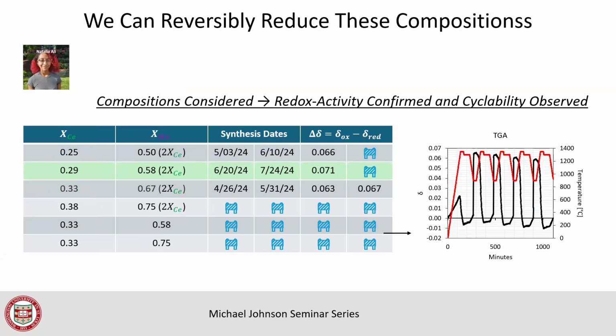She then went ahead and took those compositions and did a process called thermogravimetric analysis, TGA. TGA basically is an oven that can measure the amount of mass produced by a system. So if you were to put an ice cube in a TGA and heat it up, you would eventually see the mass of your sample decreasing and decreasing until mass is zero. So all the water is vaporized and it's no longer in the vessel that's holding it. So TGA can tell you how the mass changes as you heat the system up.